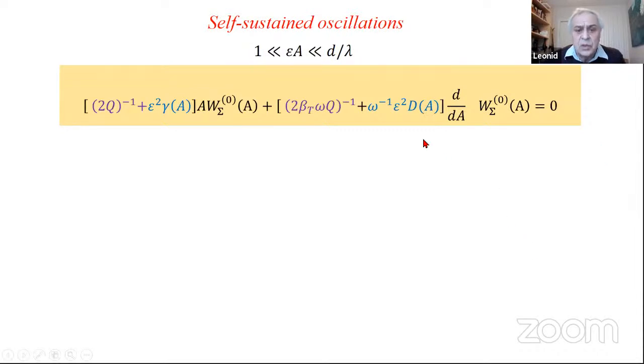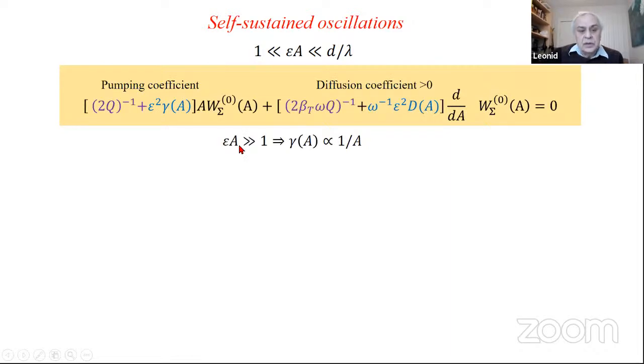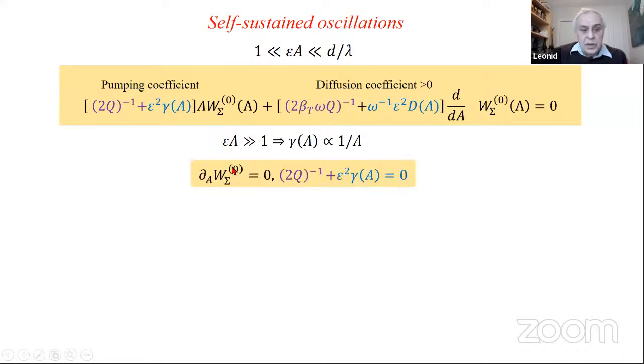Okay, final. Then what happens when we consider the excitation regime? Now we have to take into account that really this coefficient, especially the friction coefficient, and unfortunately this is a diffusion coefficient, which Robert would like to discuss, increases with amplitude. It depends on amplitude. And what is this pumping and diffusion? When this is epsilon A, a big deviation from equilibrium position, we can see that the derivative of the Wigner function equals 0 when this coefficient equals 0. So it means that this Wigner function has a maximum at this value. Of course, it's impossible when this gamma A is only positive, so it cannot be equal to 0.